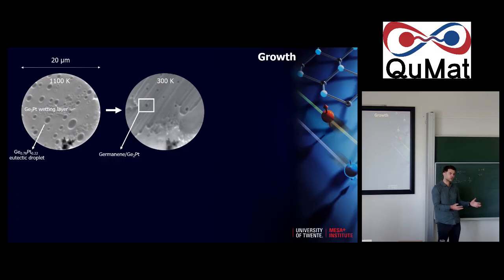We know this from Kikuchi scattering experiments. And on top of that, you see that the composition is different. You have extra germanium in the droplet. This extra germanium then will escape, and some of it, or most of it, traps on top of this crystallite. Here you see a few of them. This is a scale of 20 microns, so we talk about a range of half a micron to 1 micron. These are the 2D flakes.